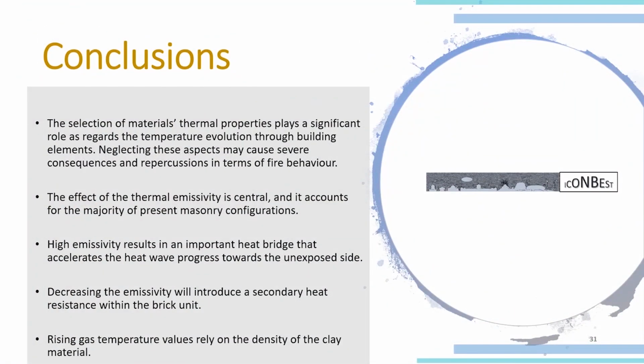To conclude, the selection of materials' thermal properties plays a significant role regarding the temperature evolution through building components. Neglecting these aspects may cause severe consequences and repercussions in terms of fire behavior. The effect of the thermal emissivity is vital and it accounts for the majority of present masonry configurations. High emissivity results in an important heat bridge that accelerates the heat wave progress towards the unexposed side. On the other hand, decreasing the emissivity will introduce a secondary heat resistance within the brick unit. Finally, rising gas temperature values rely on the density of the clay material.